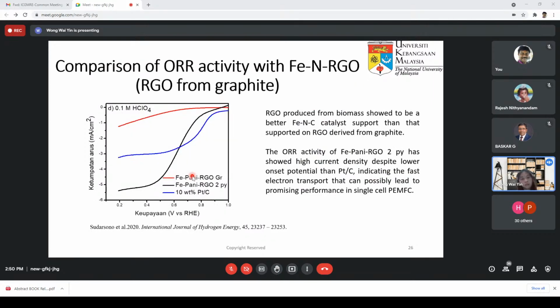Now if you compare the results, this Fe-Pani-RGO after second pyrolysis with the Fe-Pani-RGO produced from graphite, this is the result produced from the graphite. You can see that the activity is rather low as compared to the one produced from biomass, maybe because of the speculated role of the impurities and the defective sites that have contributed to the activity. It also helps to give this high current density, which increases fast electron transport, and that possibly can lead to a promising performance in the single cell.